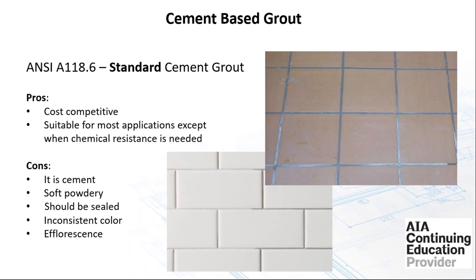You know, we see it mostly occurring, or a lot of times it's prevalent, on the side of a building. You see that white film coming down a brick building or something. That's the efflorescence. Now, there are cleaners available. However, depending on the surface of the tile, depending on the type of tile, it could be difficult to clean. And the other factor is, unless you find the mode of failure where this water is coming from, it's going to continue to happen. So those are generally the two factors in grout and why they're inconsistent.